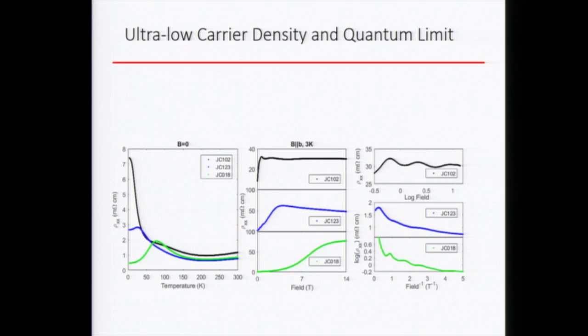And you can also infer where the quantum limit is by measuring different amounts of carrier density, right? For this material, for the green crystals, you have a peak at a finite temperature, and then you can see the SDH oscillations with a periodicity of about 1 Tesla. For the blue crystal, you have a lower peak, and you can see the SDH oscillation with a periodicity of about 0.5 Tesla. And now for the black crystal, it obviously has much lower carrier density, and you don't even see quantum oscillation anymore.